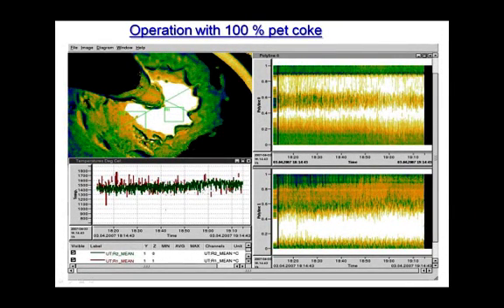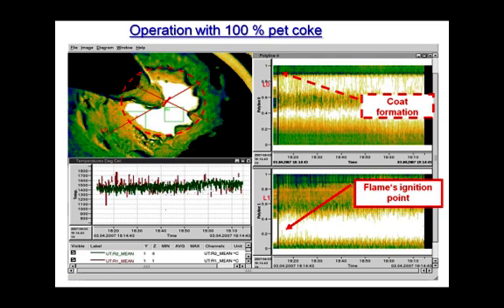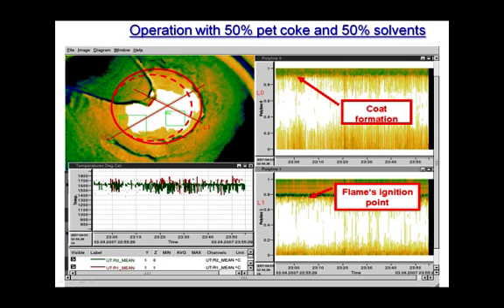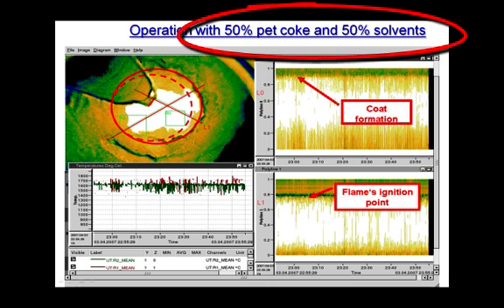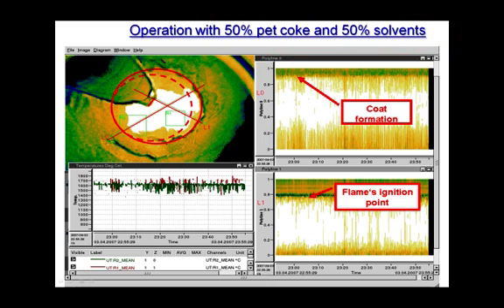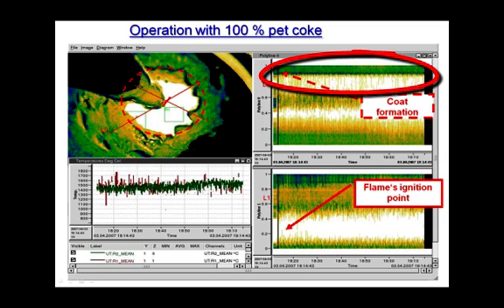This customer, for example, used 100% pet coke, and you can clearly see coating formation and the flame's ignition point in the polylines. When this customer changed operation to 50% pet coke and 50% solvents, the coating formation and the flame's ignition point changed significantly. The coating was burned off and the ignition point went nearer to the burner. If we change the slides, then you can see the comparison very clearly.